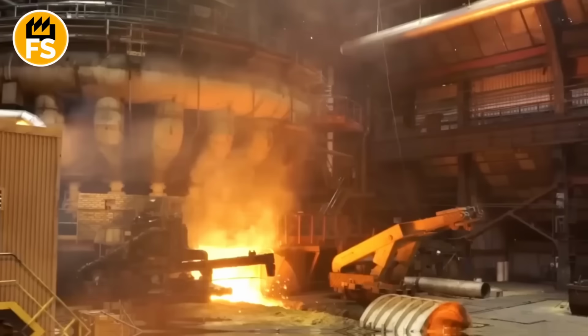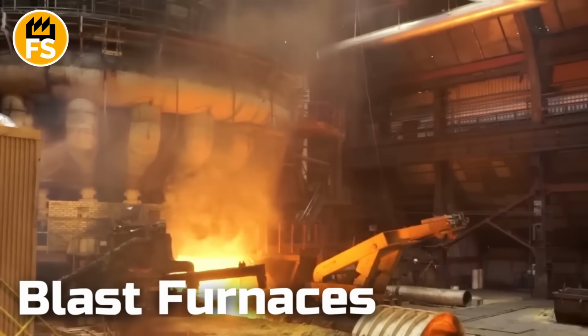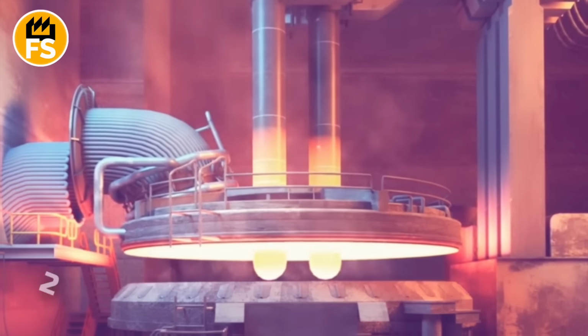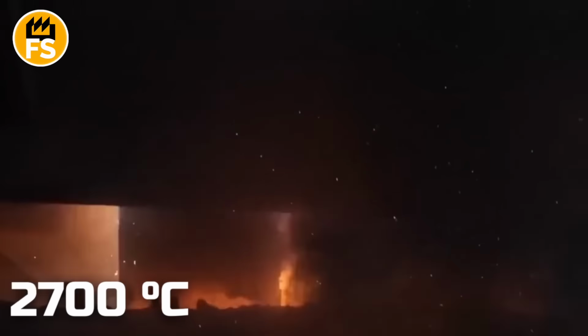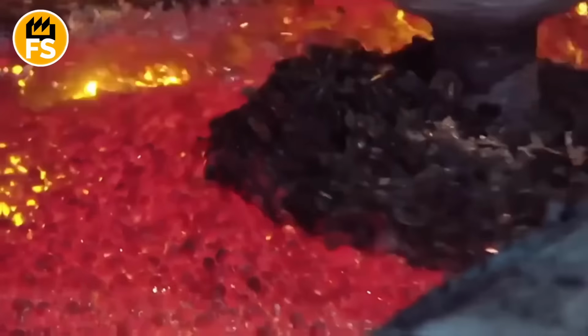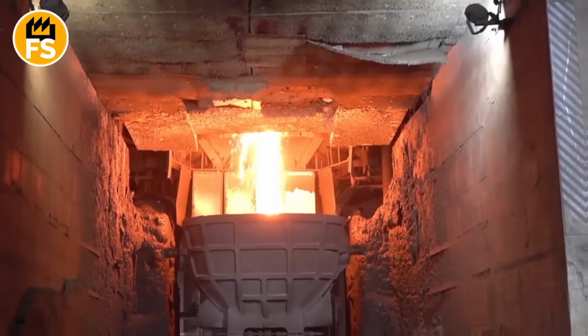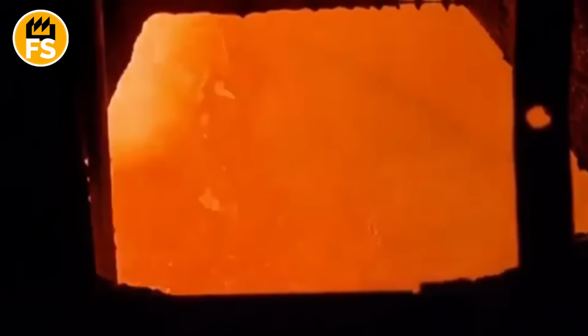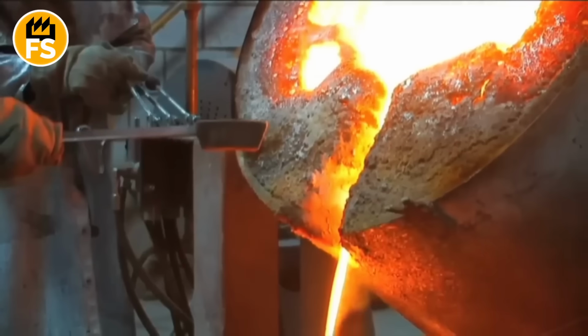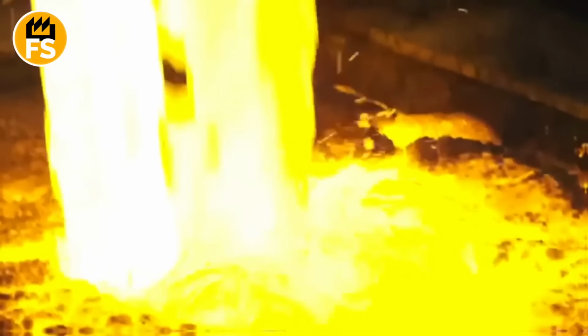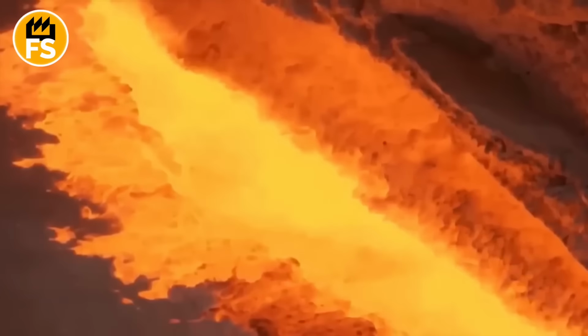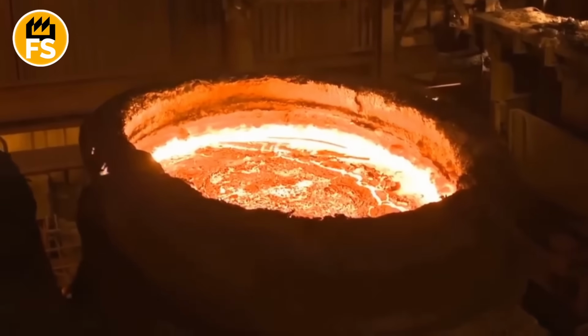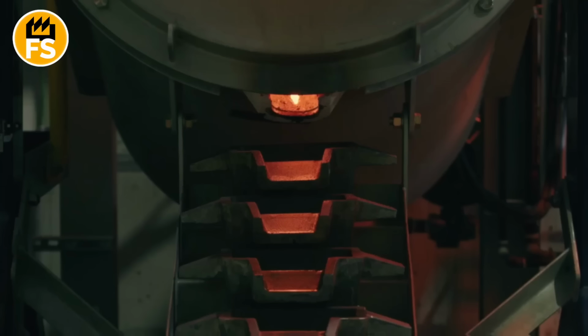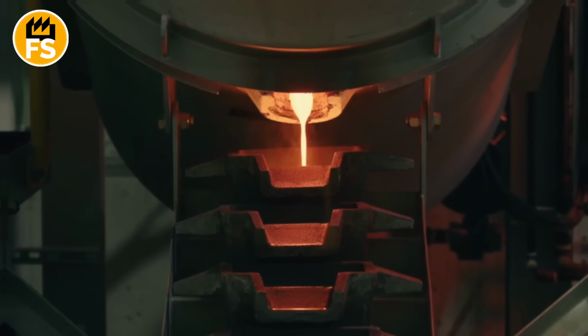Melting magnetite concentrate happens in blast furnaces, or electric arc furnaces running at temperatures over 2700 degrees Fahrenheit. Inside the furnace, a mass of ore, coke, and fluxes slowly descends, passing through zones of different heat where solid chunks first sinter together, then transition into liquid. Molten iron collects at the bottom of the furnace, while lighter components, including vanadium oxides, concentrate in the upper slag layer. When the moment of release arrives, the furnace opens, and glowing streams pour out.